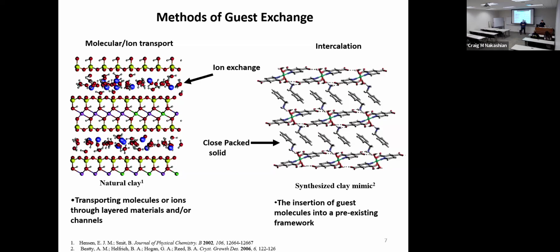I was bored one day in lab about 10 years ago or so. And I was like, yeah, what the heck, let's try it. I stuck some molecule inside, did an analysis, it was there, heat it, removed it, checked it to verify it was gone. And I was like, okay, let's do it again. Let's do it again. Up to 10 times. Framework maintained its complete integrity from removing and insertion. Clays, we may not get that ability. Because then we've got to start worrying about other things going inside of our clay itself, which will kind of degrade the exact clay material.